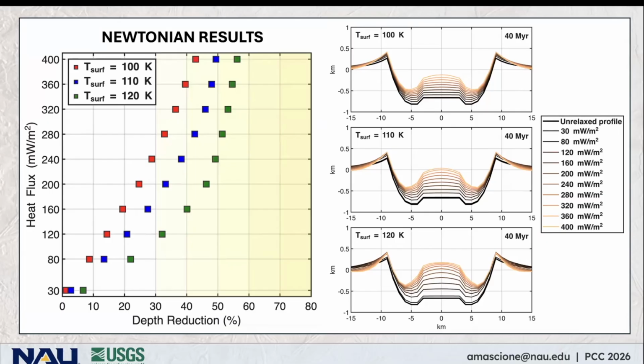At a conservative surface temperature of 100 Kelvin and heat fluxes of 30 and 80 milliwatts per square meter, there was less than 10% depth reduction. Even at a surface temperature of 110 Kelvin, we did not get depth reductions exceeding 15% if we invoke those modern heat fluxes. And it's not until we assume significantly higher heat fluxes that we begin to see depth reductions exceeding 30%.